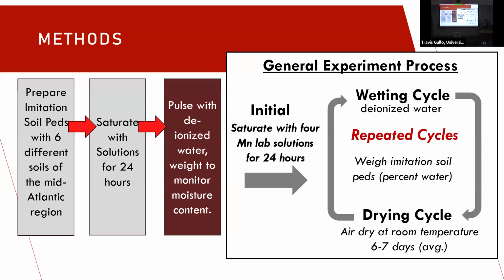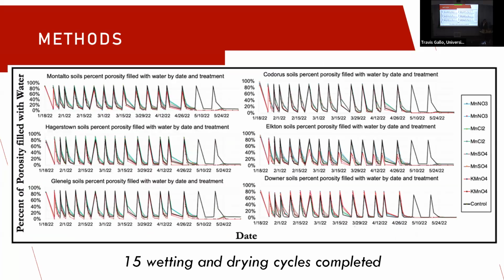After saturating with the solutions for 24 hours, this is the general process of the experiment. So you have a wetting cycle using deionized water, and then a drying cycle where they air dry at room temperature for 6 to 7 days, and then it repeats. And we weigh the imitation soil peds to obtain the percent water in between to get an idea of how wet or how dry they are and have some documentation of that. There were 15 wetting and drying cycles completed, and you can see that the soil moisture behaved rather similarly across all soils tested.